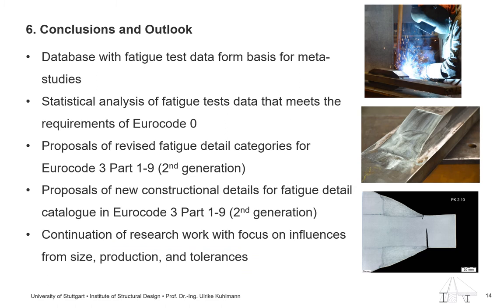Let me sum up the main points of the presentation. I presented a database for fatigue test data to collect information about fatigue tests — a very useful tool for meta-studies on fatigue strength. I presented a statistical approach to derive fatigue strength from scattering data that meets the requirements of Eurocode 0. As an example, I presented studies on two common details — gusset plates and butt joints — and concluded that the fatigue strength of these details could be improved. Based on new tests, I presented proposals for the classification of constructional details new to the fatigue detail catalog: the lamellar joint and the weld-off cover plates. The research work will continue in a follow-up project with focus on influences from size, production, and tolerance, and the database should also continue to be filled with fatigue test data.